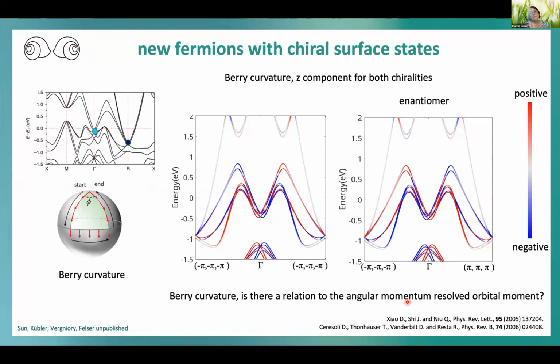Okay, so but can we see the Berry phase, as we know from the anomalous Hall effect in magnetic systems? So we could look for the Berry phase character, the sign, in these chiral materials, for every band. And there's a Berry phase here. We looked along the 1-1-1 direction, which is the gamma to R direction, which is the most interesting direction for us.